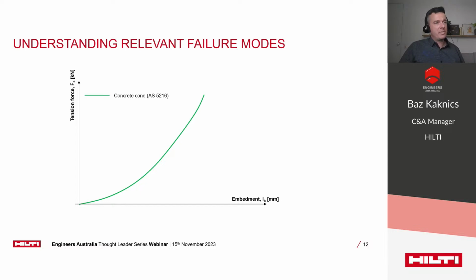Let's go back to our diagram and include the bond failure that we just discussed. As we said, the linear function will be valid up to 20D embedment, beyond which the efficiency of the bond slightly decreases. Now, in a similar fashion to AS3600, it is important to account for a potential splitting failure for situations where the concrete cover is limited, for example, small bar spacing or small edge distances. In case the splitting failure would occur before the bond strength could be developed, then we obviously won't be able to reach the full bond capacity of the anchors.